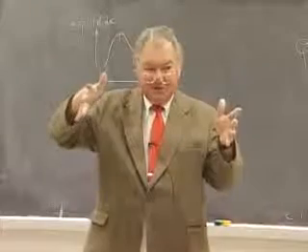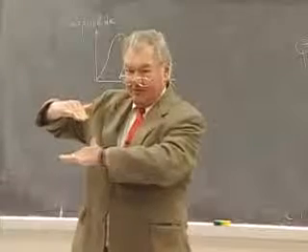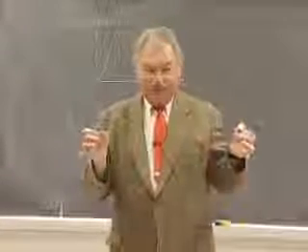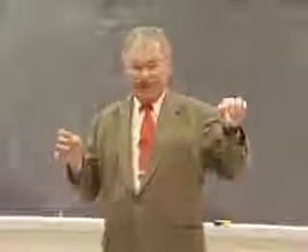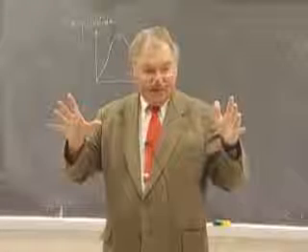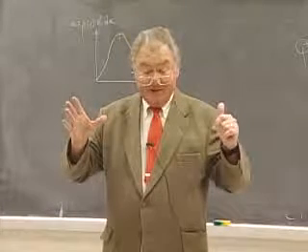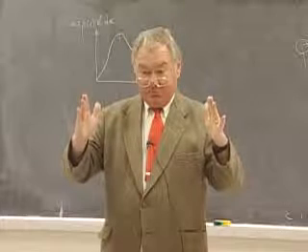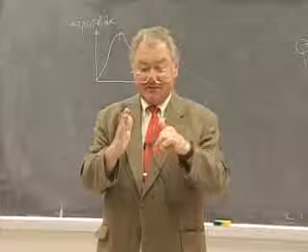And it's really tetragonal. But there are going to be domains, a tetragonal domain in one orientation here, a tetragonal domain in another orientation here. So he gets himself a random number generator and takes numbers 1, 2, and 3 and puts them on a cubic lattice to determine what the distortion will be. So, hey, I got a bunch of 1s here and a bunch of 3s here. This crystal is built of domains. And the reason the silver ions migrate rapidly is that a domain can pop from one mode of distortion to another, and that's essentially going to transport the silver ion from one end of the domain to another. This guy got 2 papers out of it.